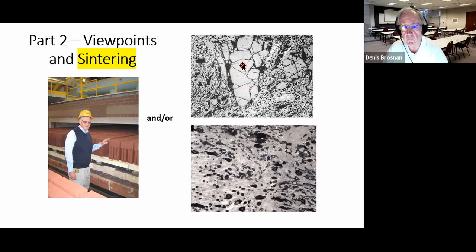It's all fractured up. And we'll talk about why that happens in volume transitions that take place in heating of quartz and additional volume transitions as the quartz is converted to other minerals. But these quartz grains, there are a few of them here in this picture, are surrounded by what we would typically call a matrix. The matrix is the vitrified ceramic that was formed by the firing process, and the black spots are pores in the ceramic. They're black because we're only seeing light that's reflected directly upward, and the pores tend to scatter light, so they appear to be black in this photograph.